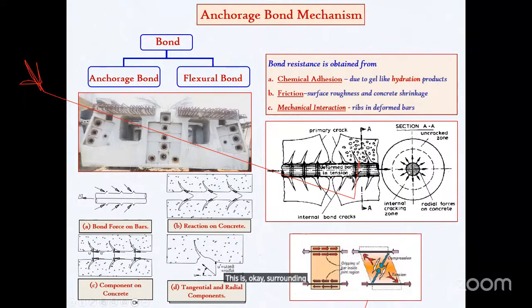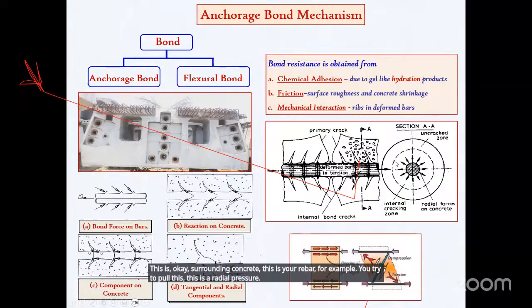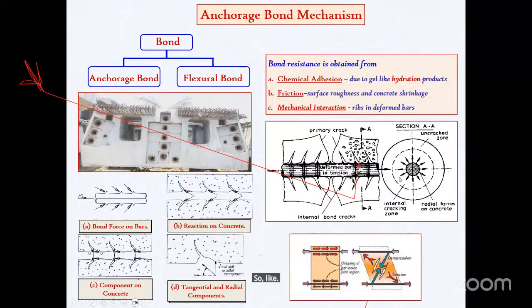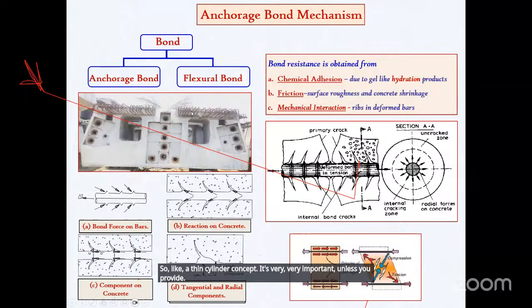This is your rebar, for example. You try to pull this. This is the radial pressure. The radial pressure is acting to split the concrete, like a thin cylinder concept. It's very, very important. Unless you provide sufficient length of anchorage reinforcement here, you cannot withstand the bond stresses developed. Otherwise, there is going to be split cracking below the reinforcement bar up to the bottommost, and in the horizontal direction between the rebars, and on the side we have the side cover.